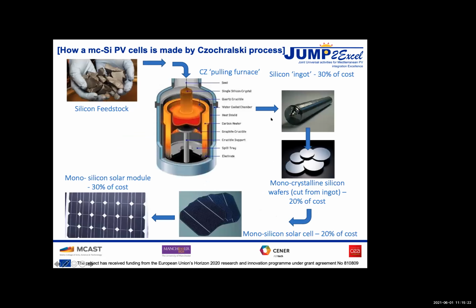And then for monocrystalline silicon, what we do next is we melt it in a furnace, which is basically a silicon dioxide crucible. You heat that up to huge temperatures of 1400 degrees C or whatever to melt the silicon, and then you put a single crystal seed into here, and then you draw it out and rotate it, so that you get a large boule, a single crystal of silicon, which is shown on the left in the ingot. That's then sliced up, and then you do lots of processes, diffusing in contacts and dopants to create a solar cell. And here we are. So that's actually out of date. It's less than that now, as I'm going to show you.